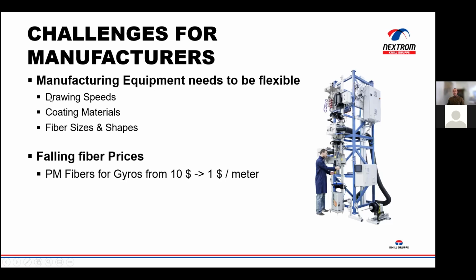For the different fibers, for a variety of different reasons, you have a wide range of different drawing speeds. The most basic reason is during the fiber draw, the fiber needs to cool down enough before you can put a coating on it. For a standard acrylic coated fiber, most of the time that's done just purely by letting it cool down in the air, and that will then limit your drawing speed accordingly. The larger the diameter fiber, the more heat, the more energy you have stored in that, and therefore the slower the draw speed. You can add forced cooling with helium, but there's a cost to that because helium is an expensive resource.